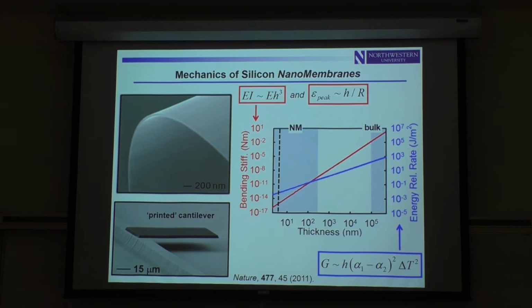So if you think about the bending stiffness of any material, it's dependent on the intrinsic Young's modulus, the mechanical properties of that material, but also depends on the geometry, in particular the thickness. So the bending stiffness decreases like the cube of the thickness. So when you go from a wafer that might have a thickness of 1 millimeter to a silicon nanomembrane, which might have a thickness of 10 to 100 nanometers, because of that cubic thickness scaling of the bending stiffness, you decrease that parameter, the flexural rigidity, by maybe 14, 15 orders of magnitude. And that is just Newtonian elementary classical mechanics. But again, you change any kind of physical parameter by 15 orders of magnitude, it really changes the way you think about the material.